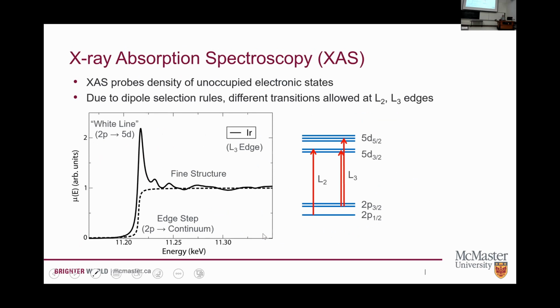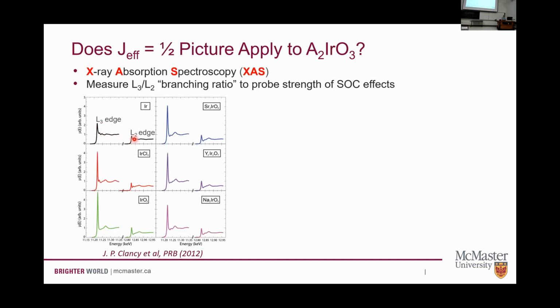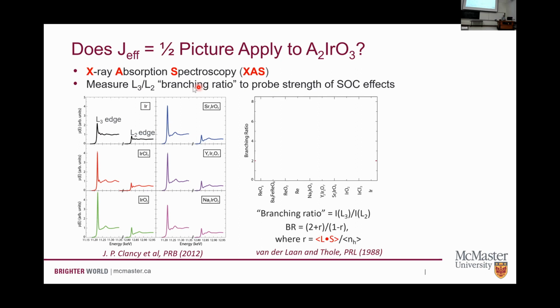All right. We can also do X-ray absorption spectroscopy. Again, this is another thing where we tune to absorption edges. There are different transition rules associated with these. And the important thing is that it gives us a way to map out the empty electronic states. Okay. And so if we look at where these electronic states are, we can compare different transition rules, so different absorption edges. So we get something that's called the branching ratio that gives us the ratio of these unoccupied states, how many states are available. Okay, and it turns out that we can relate this to the strength of the spin orbit coupling and pull out a measure of the L·S. This is the expectation value of the spin orbit.